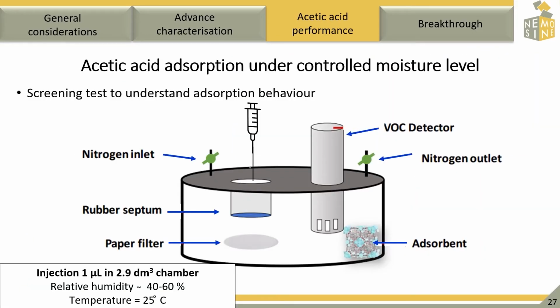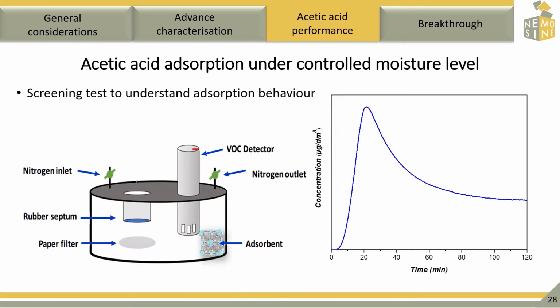For this, adsorption experiments in a closed and under-controlled humidity chamber can be performed. This method acts as a screening test to understand adsorption behavior of our materials. The samples are placed in the sealed chamber at room temperature and under controlled moisture, and left around 90 minutes to equilibrate with the moisture content. After that, 1 microliter of acetic acid is injected through an injection port. The variation of the concentration of acetic acid inside the chamber is then recorded as a function of time.